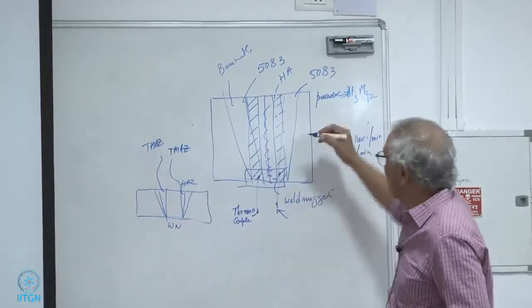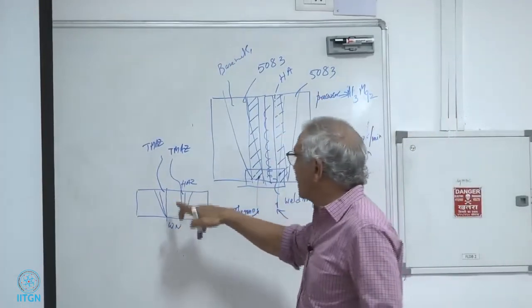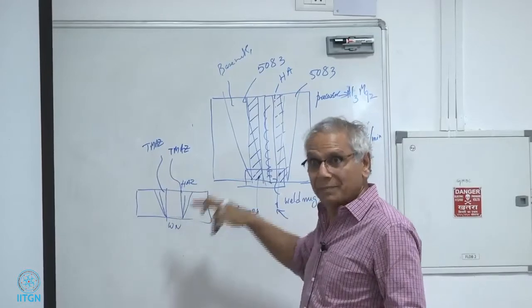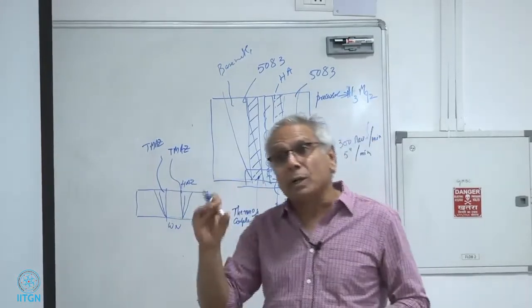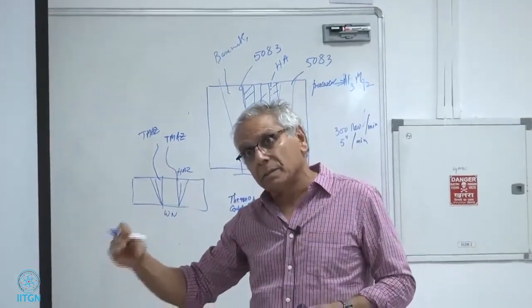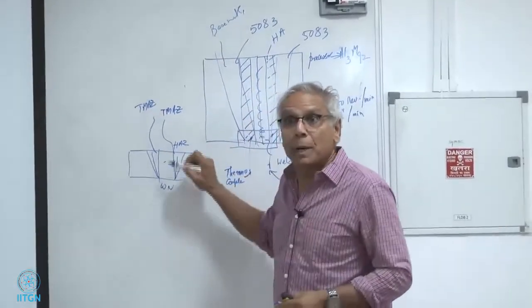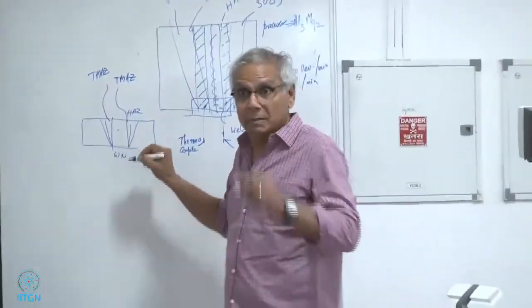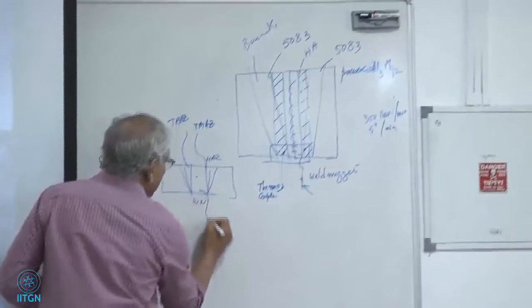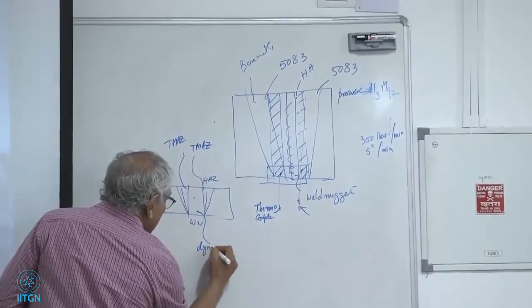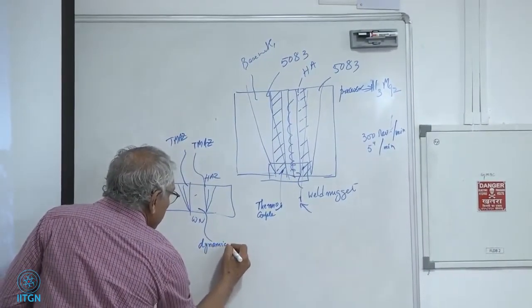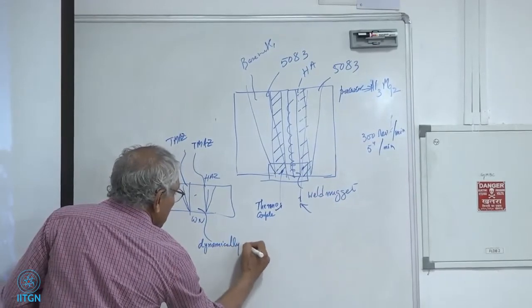Thermomechanically affected zone, I forgot about that, right? So you have the weld nugget, the thermomechanically affected zone, and the heat affected zone. I will document all the precipitates. What are the precipitates here? You probably have a dynamically recrystallized microstructure here, with no precipitates.